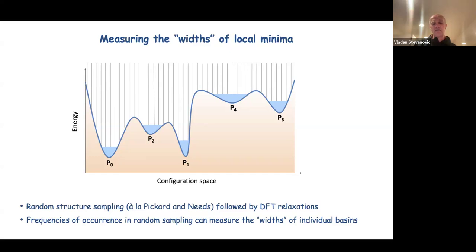They actually created it to search for the ground state, but random structure sampling can actually provide a statistical representation of the potential energy surface, and it pretty much works as follows. You basically create a random box, so random unit cell parameters, and throw atoms randomly inside the box, and then use first principles methods to relax that structure, which has periodic boundary conditions imposed on it, to the closest local minimum on the potential energy surface.